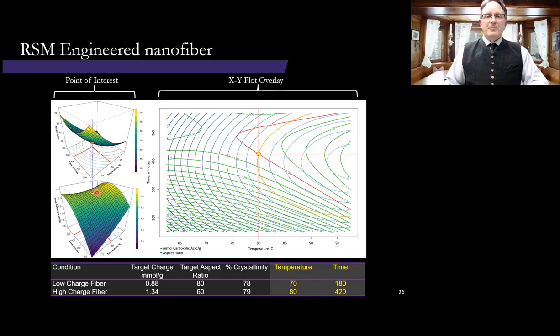Same with surface charge. But as you can see, the 3D surfaces do not present a really useful tool for performing that analysis. So to provide a better visualization, on the right, I overlaid just the XY data for the RSM model for these plots, and selected the point at which both plots intersect. So this is the charge target for the high, 1.34, the aspect ratio of 60, and then I can pretty easily from here identify that 80 degrees is the temperature of treatment and 420 minutes is the time. And this is summarized here in this table.